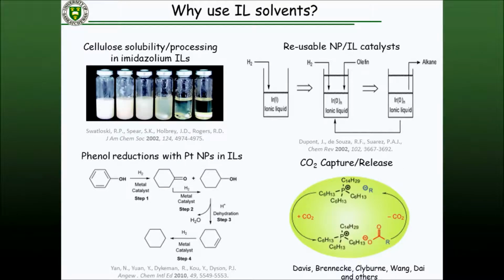solvents for cellulose solubility. So we can actually dissolve cellulose and break down cellulose in ionic liquids at essentially room temperature conditions. The idea of reusing nanoparticle catalyst in ionic liquid, bringing in a substrate, taking out a product, and just keep reusing that system. Taking phenols, for example, that might come from lignin, and being able to hydrogenate phenols and hydrodeoxygenation routes to make